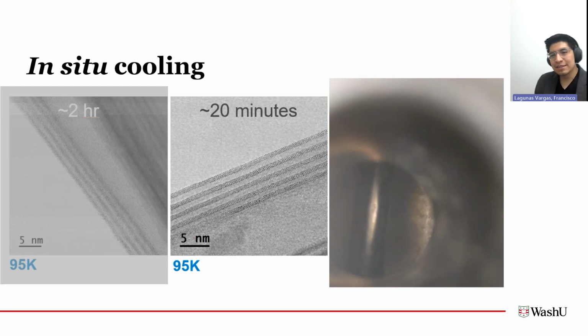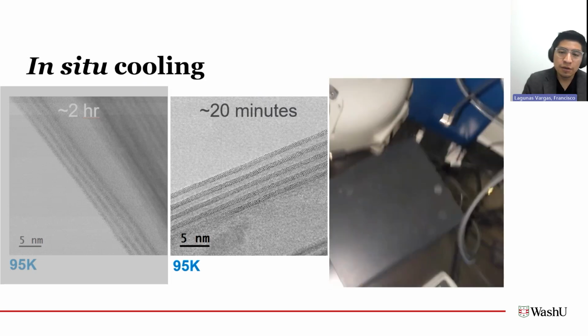So this takes your window on the microscope that you could use to get high quality data, as opposed to being on the microscope for 8 hours and having, let's say, 6 hours of active time to acquire high quality images, and reduces that window down to about 20 minutes. And so you can imagine that these cryogenic experiments can be quite challenging. And if you have to keep track of a lot of different things while you're on the microscope, it only complicates things further.